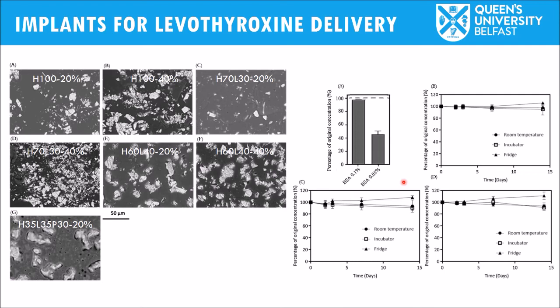So it was achieved, 14 days of stability were achieved, while if the protein was not present in the aqueous environment, the drug was quickly degraded in a few hours. Okay, so to do implantable devices, you need the drug to be stable for at least 24 hours to be able to quantify it in the release medium. So obviously it was not easy, but the stability increase of the drug was achieved by adding bovine serum albumin, and the stability was tested for up to 14 days.